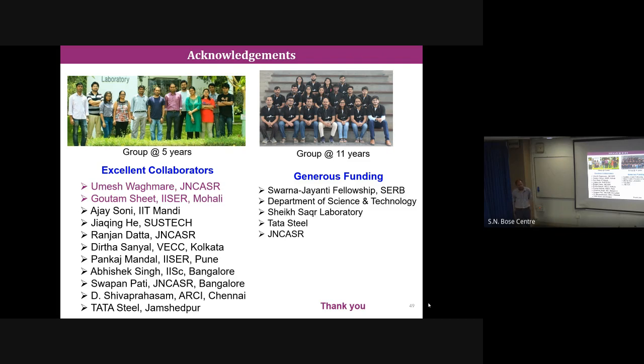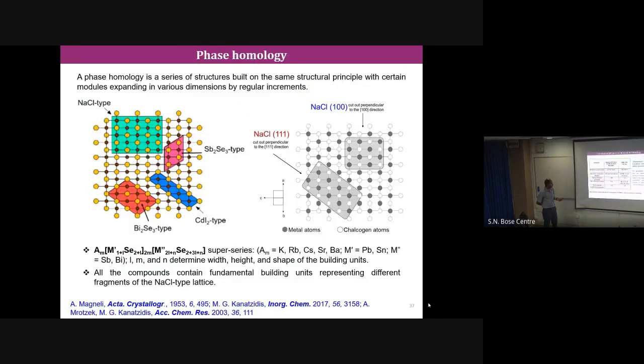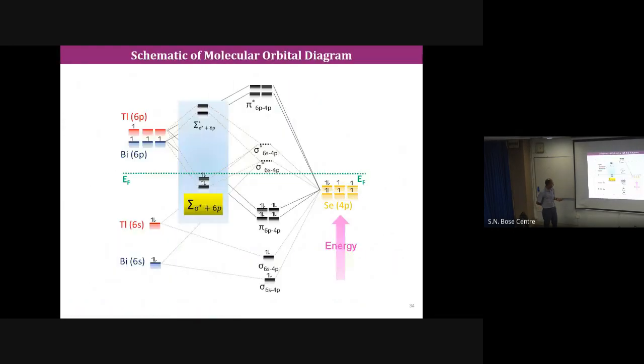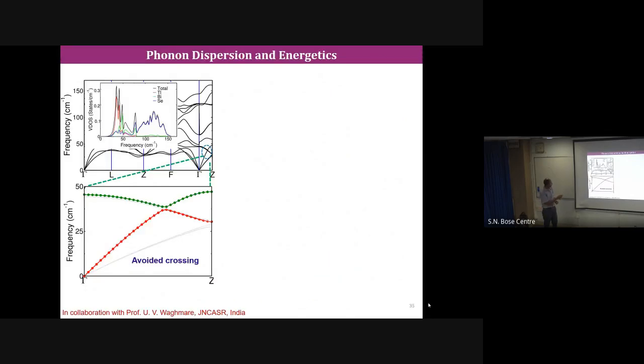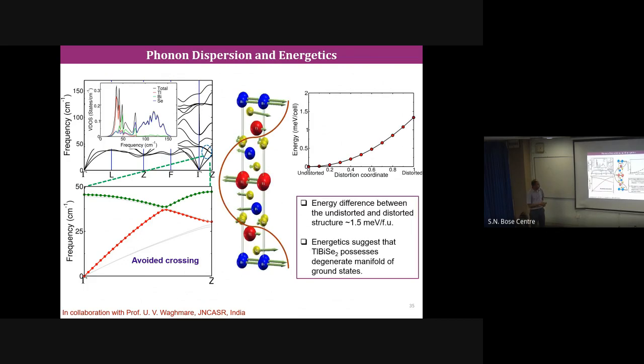In that structure, at the thallium layer, is there a phonon mode associated with the thallium layer and charge transport to another layer? Very good question. See, thallium and bismuth are both heavy, so we believe both contribute, as the phonon calculation shows. Thallium contributes more at low energy because it is much heavier, but bismuth also has a contribution. But charge transfer fully happening to this layer, of course we thought about that claim, but we don't have proof right now, so I don't say it. But in some of the compounds we made, it actually creates channels for phonons, with different routes.